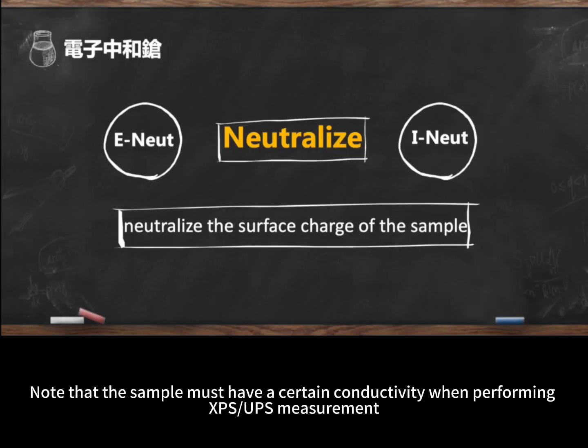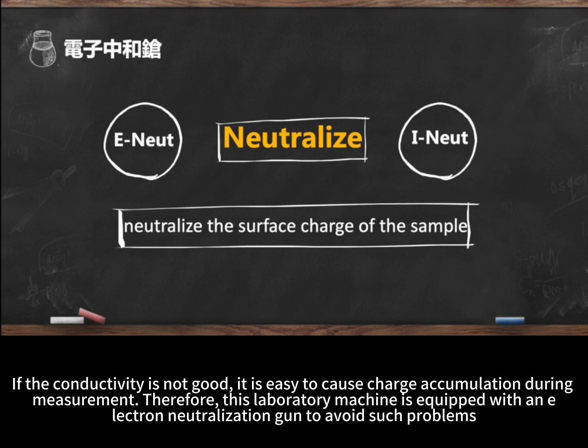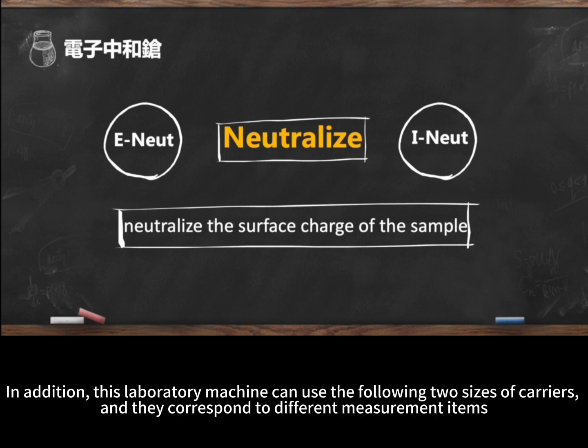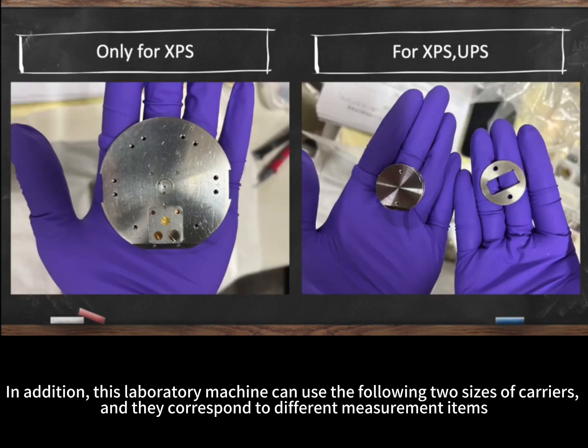Note that the sample must have a certain conductivity when performing XPS/UPS measurement. If the conductivity is not good, it is easy to cause charge accumulation during measurement. Therefore, this laboratory machine is equipped with an electron neutralization gun to avoid such problems. In addition, this laboratory machine can use the following two sizes of carriers, and they correspond to different measurement items.